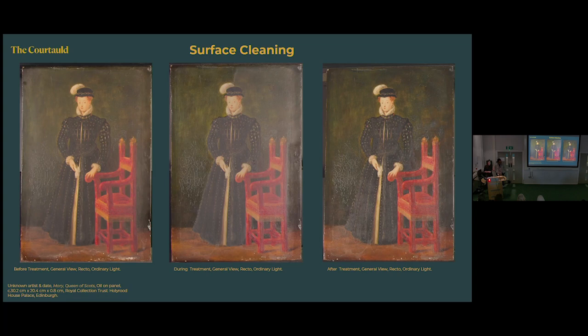So when the painting initially entered the Courtauld Conservation Studio, it was covered in a considerable layer of surface dirt, which did not only obscure the finer details of the paint application, but also would potentially hinder the efficacy of various technical analysis methods, which could then be used to paint a better picture of the painting. So as a result, even though the portrait had only initially entered the department for examination, the Royal Collection very kindly gave me permission to surface clean the painting, which I conducted using saliva applied mechanically with cotton swabs before clearing in the same manner with deionized water.